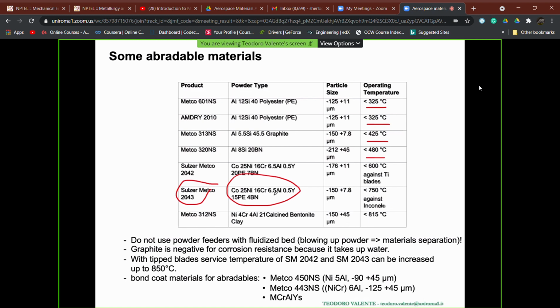For example, a metallic phase: cobalt, nickel, chromium, aluminum, yttria. In some cases, also a plastic material, polymer-based materials, and ceramic materials, like this one, which is the best known, boron nitride, which acts as a self-lubricating material, thus also allowing the exfoliation of the abradable coatings, the consumption of the abradable coatings during the working life and working exercise of our blade.